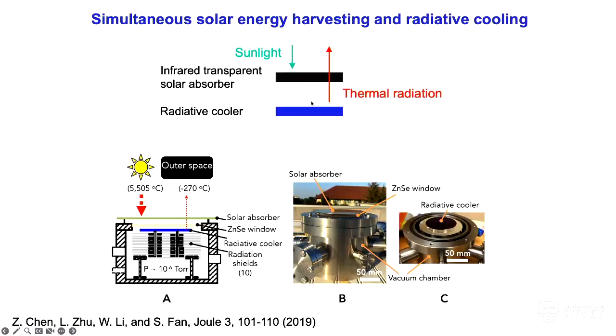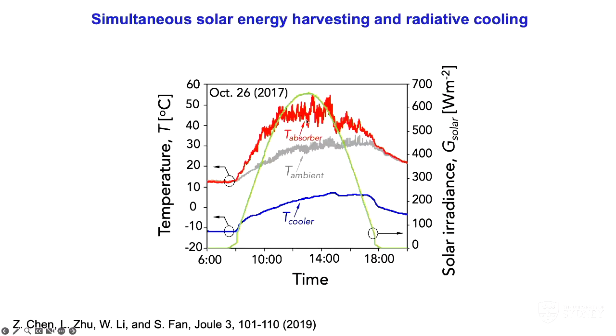So here is one experiment carried out by Zhen Chen, where we put a solar absorber on top of a radiative cooler. And we designed the solar absorber so that it absorbs sunlight, but is transparent in the mid-infrared wavelength range, so that the radiative cooler underneath it can still radiate the heat out through the solar absorber to the outer sky. And in the experiment, we see that under the sun, the solar absorber indeed heats up, indicating the harvesting of solar energy. In the meantime, the cooler still has a temperature that's substantially below the ambient air temperature, and that shows that it is possible to simultaneously harvest solar energy while performing radiative cooling.